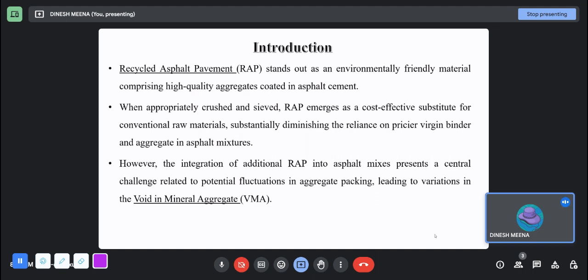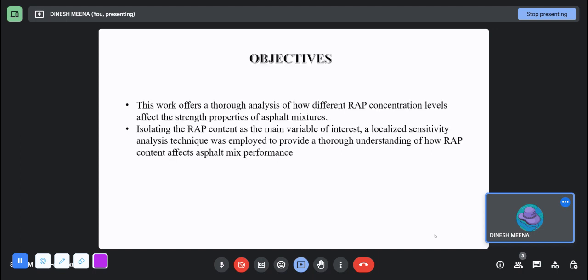However, the integration of additional recycled asphalt pavement into asphalt mixtures presents a central challenge related to potential fluctuations in aggregate packing, leading to variations in the voids in mineral aggregate, VMA. Objectives. This work offers a thorough analysis of how different recycled asphalt pavement concentration levels affect the strength properties of asphalt mixtures. Isolating the recycled asphalt content as the main variable of interest, a localized sensitivity analysis technique was employed to provide a thorough understanding of how RAP content affects asphalt mix performance.